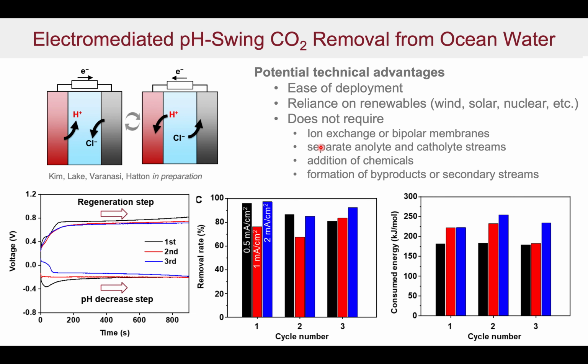Some of the preliminary results we show here are different applications of current, and they show the regeneration step and the release step, and how these cycles are pretty good. And we can show that we got removal rates that are pretty respectable, around 70 to 80% in general. The energetics are still a little high, but this is acceptable at this stage, and we know we can reduce these to some extent by better design of the electrodes and the flow patterns and the like.